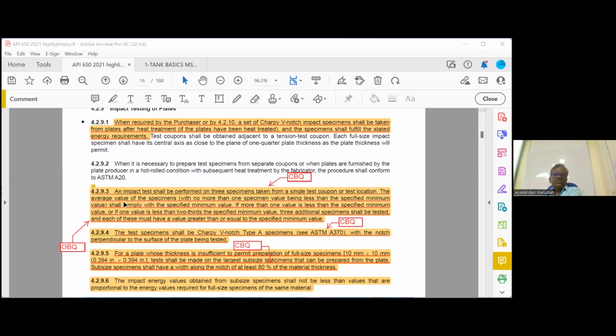The next one, this is what I said. The average value of 3 specimens, with not more than 1 specimen being less than the specified minimum value, shall comply with the specified minimum value. There is a mistake here actually. Here it should be specified average, just cut and write average. There is a mistake in the code. If more than 1 value is less than the specified average value, or if 1 value is less than 2/3 of the average value, 3 additional specimens shall be tested. Wherever minimum, you have to put average. They just printed it as minimum, it will be confusing.